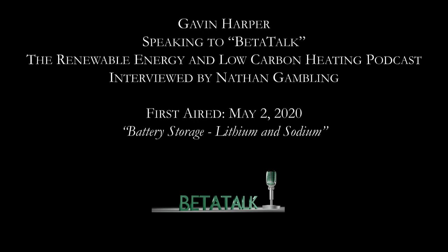So we will be testing that and understanding the lifetime and also the efficiency. The efficiency for a battery is, if you put 1 kilowatt hour of energy in, how much do you get back out to use? With lithium ion batteries, that's in the high 90s, so it's not really anything to worry about. With flow cell batteries, that can be lower. What we want to understand is, does how we operate it change the efficiency? That is the research we'll be doing, to understand how we can get the best efficiency out of it. We think this has got potential for stationary storage. So that's quite an exciting development that is first on the jobs list when we're allowed back on site.